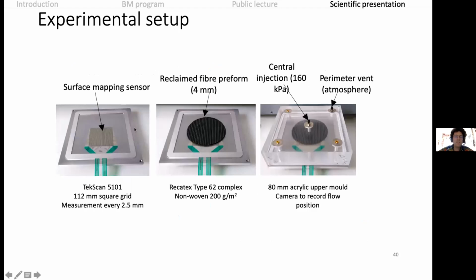So typically what James did in Bristol is building a mold. He put a flat plate, he put the pressure sensor in here. We put the reclaimed material, so a disc. We chose to use a disc, circular geometry. We put it on the sensor, and we close the mold with a lid. And it's a transparent lid in plexiglass, so that's pretty cool because we can see, in the next slide, the resin flow. We're going to inject the resin from the center, and it's vented on one side.